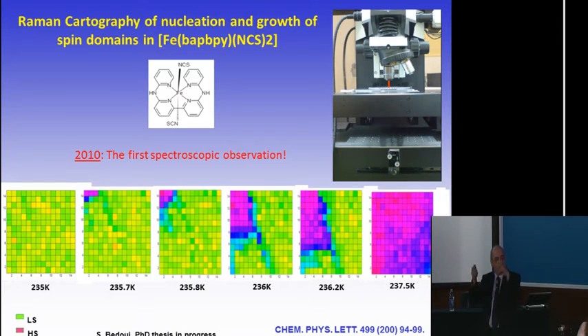So what we did, we took just one crystal, through a microscope with Raman spectroscopy, and we did imaging on the crystal. Here are the Raman spectra, the imaging by Raman spectroscopy. When we have the band of low spin, it's yellow. When we have the band of the high spin, we give the pink color. You see, when we are in the low spin state here, everything is low spin. So with the imaging by Raman spectroscopy, we can see spectroscopically that the surface is in the low spin state.